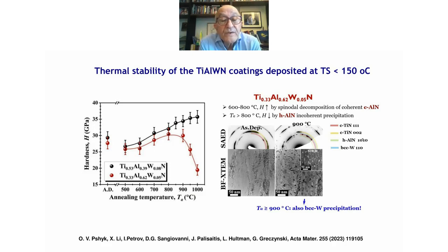So we wanted to study the thermal stability of these films, and here we have titanium aluminum nitride, the red curve. The red curve is aluminum nitride rich, 62%. This shows hardening and softening, just like for titanium aluminum nitride, and the diffraction pattern, the TEM, shows that these films do have aluminum nitride phase separation at 900 degrees, but also BCC tungsten. The dark spots, which is only 40% aluminum nitride, are more stable. There is no softening. So that was puzzling. Next slide.